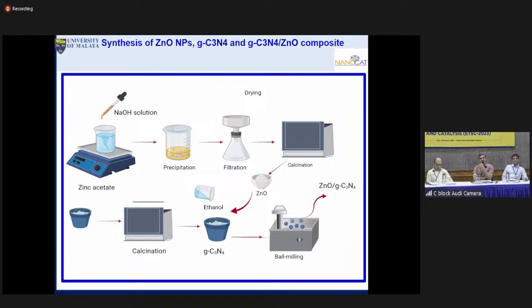First we prepare the zinc oxide, using zinc acetate as the precursor mixed with water, and then we add sodium hydroxide solution as a capping agent. After we get the precipitation, we go to filtration and calcination. Finally, we get the zinc oxide.